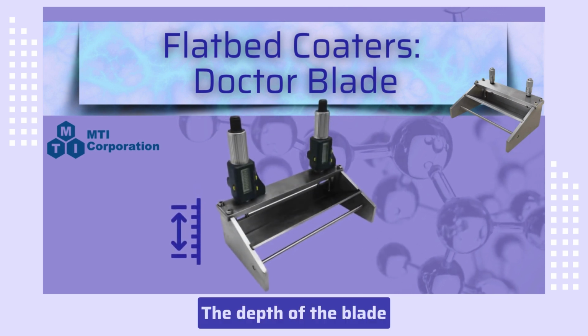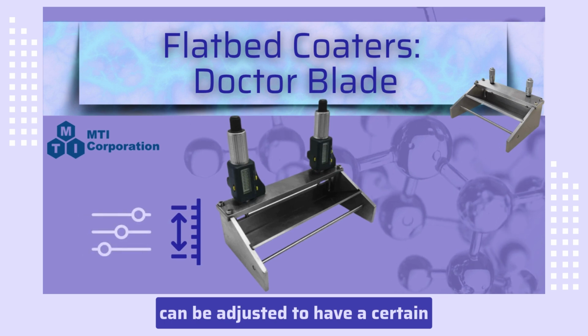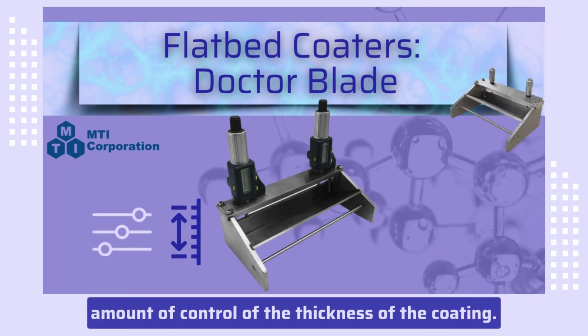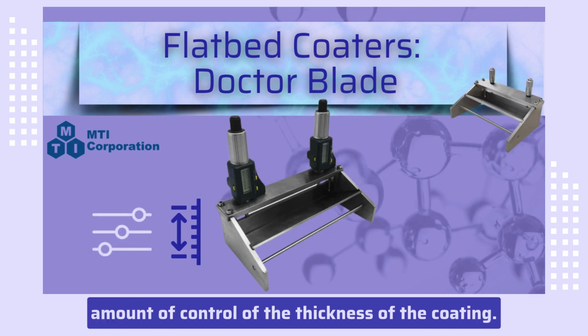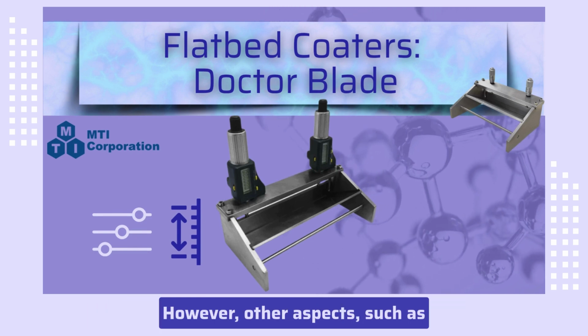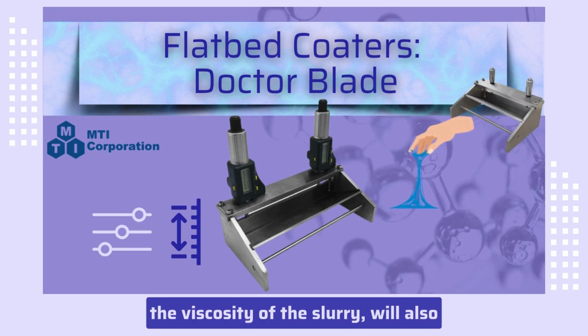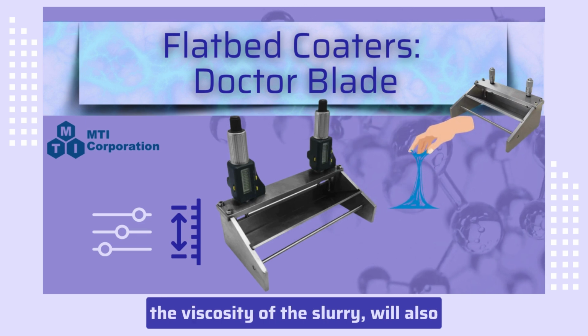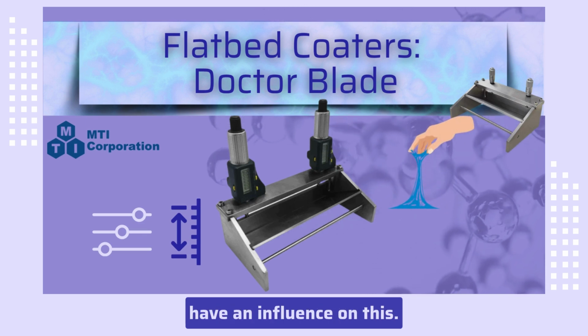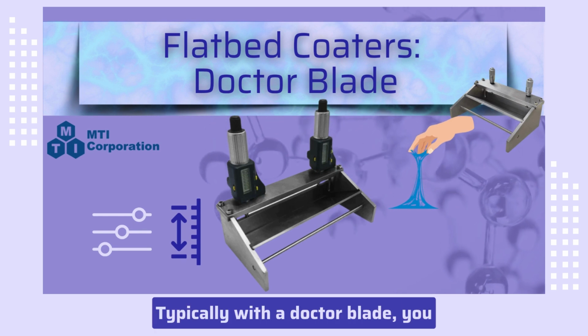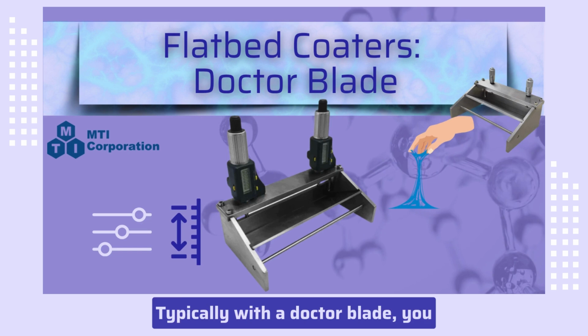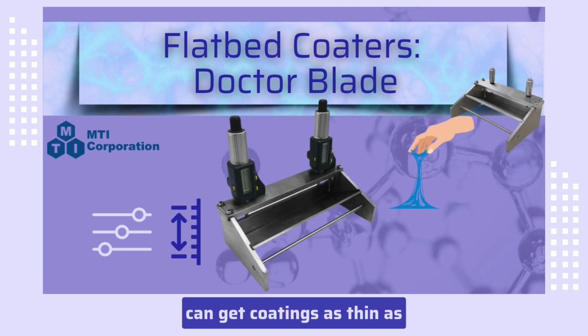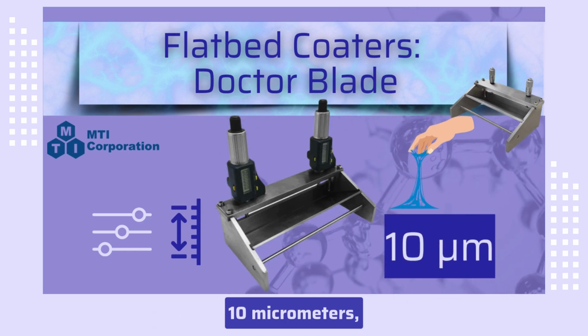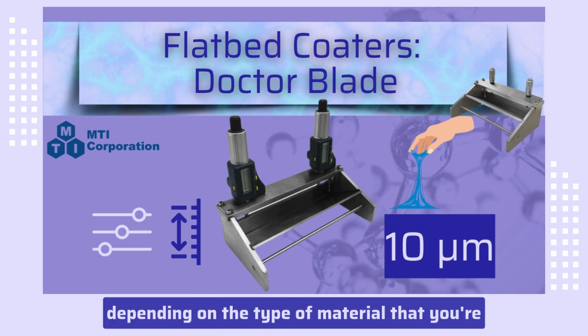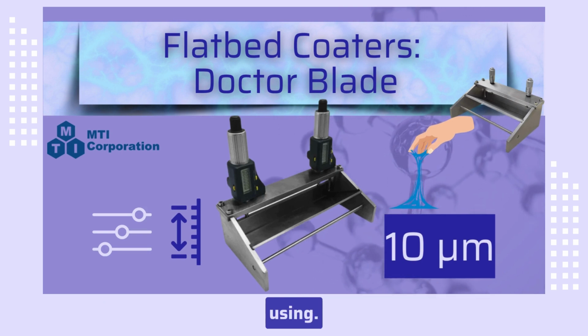The depth of the blade can be adjusted to have a certain amount of control of the thickness of the coating. However, other aspects such as the viscosity of the slurry will also have an influence on this. Typically with a doctor blade, you can get coatings as thin as 10 micrometers, depending on the type of material that you're using.